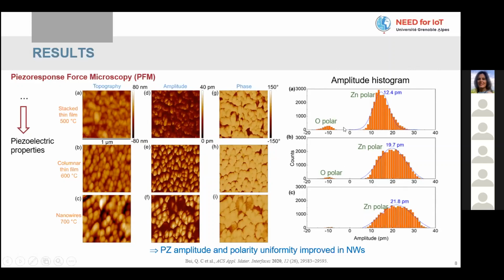And also we see that the signal on the oxygen polarity histogram is less on the nanowire, so it's more uniform. This means it's more favorable for the piezo application, because two opposite polarities can cancel out each other's signal when we build the devices.